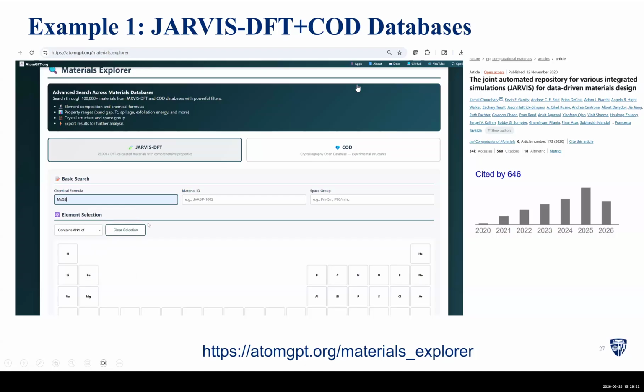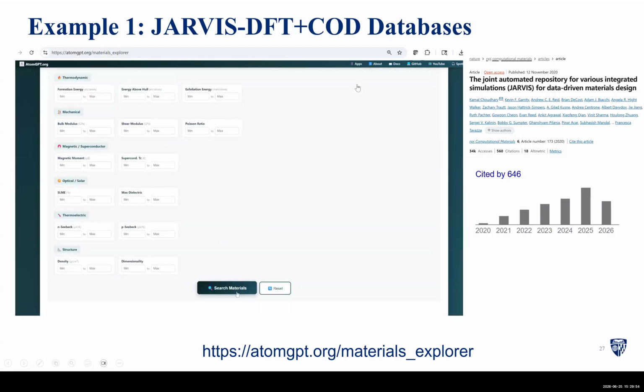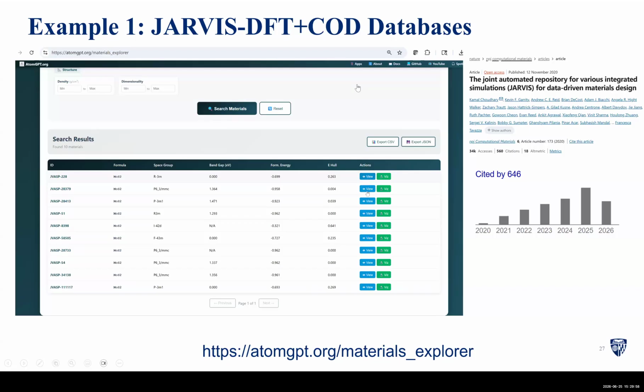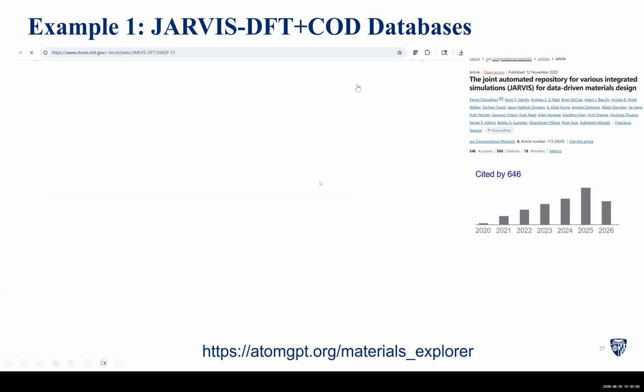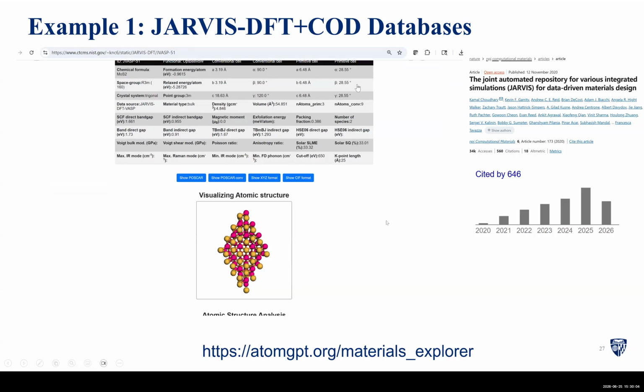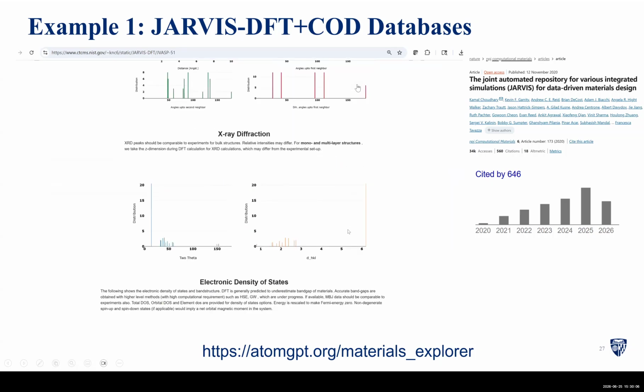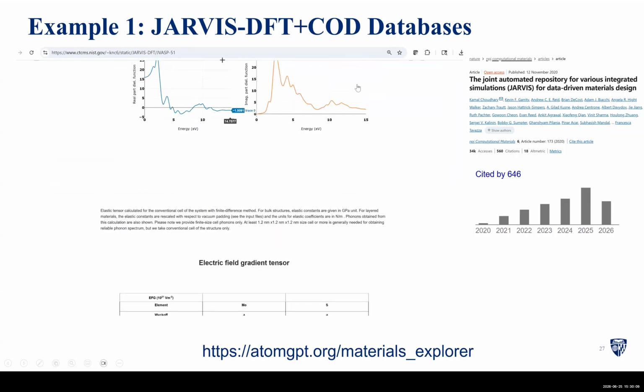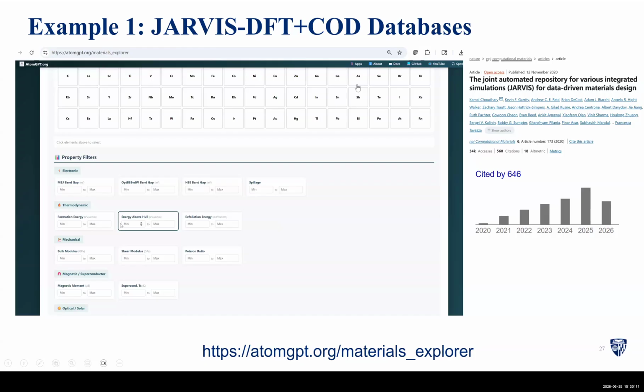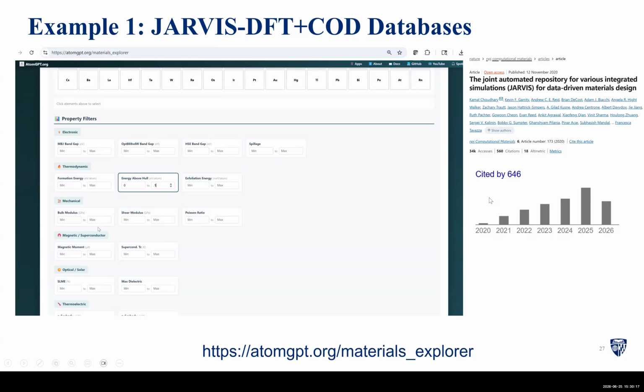tools. So for example, if you're looking for a material like MoS2, you can search MoS2 and it will give you, for each material, the details of the structure, its phonon band structure, electron band structure, Raman spectra if available, infrared spectra, dielectric function, electric field gradient, elastic tensor, and many other properties. This was published in 2020, about 700 citations.